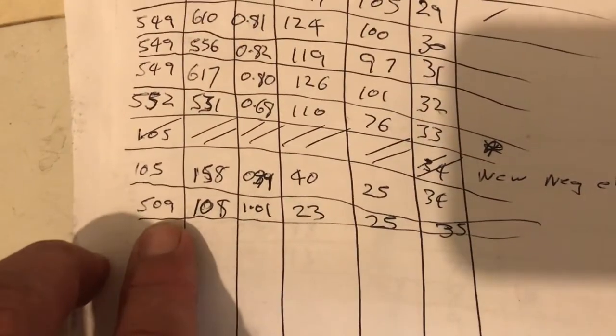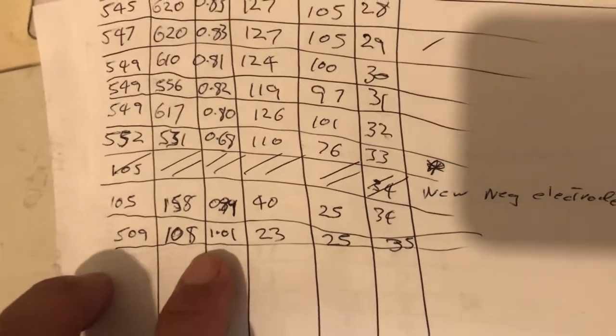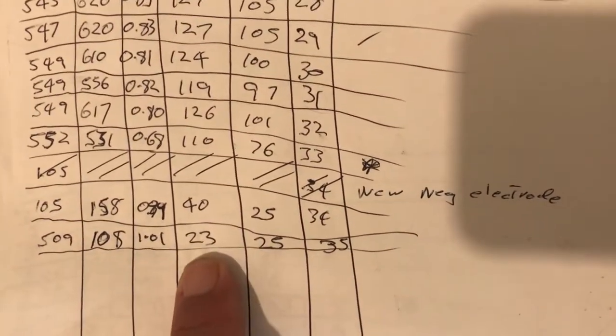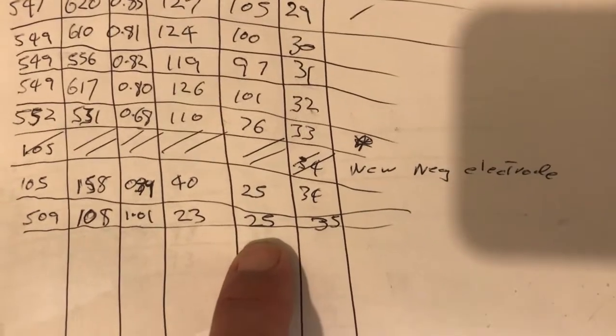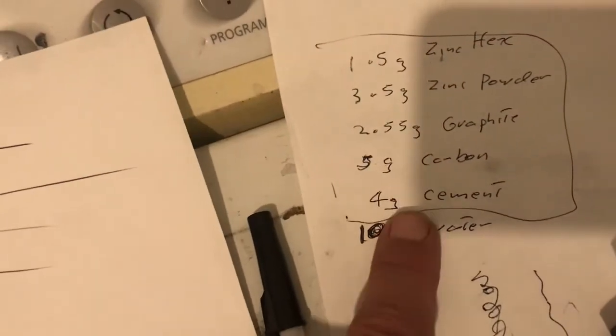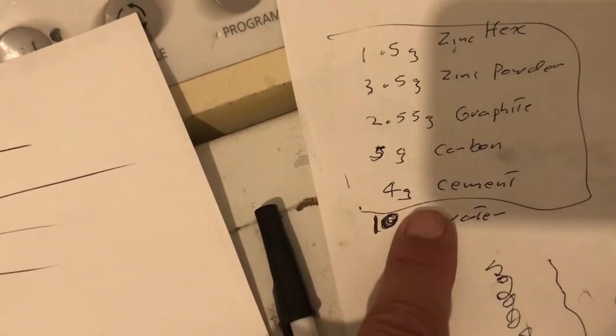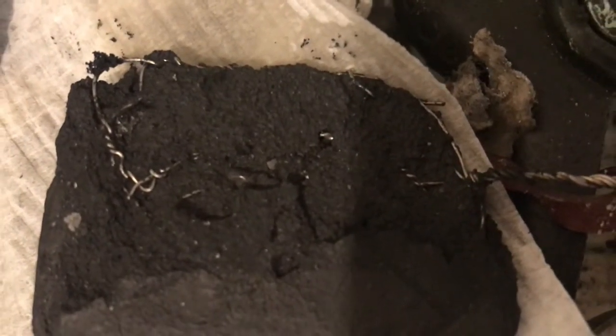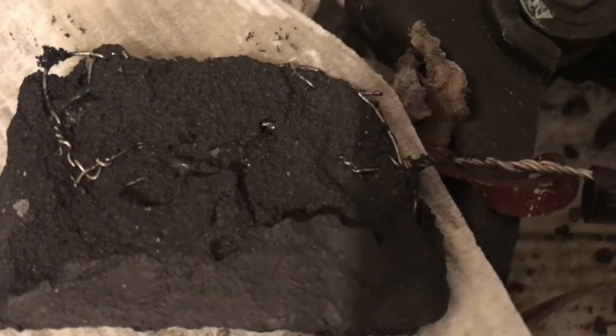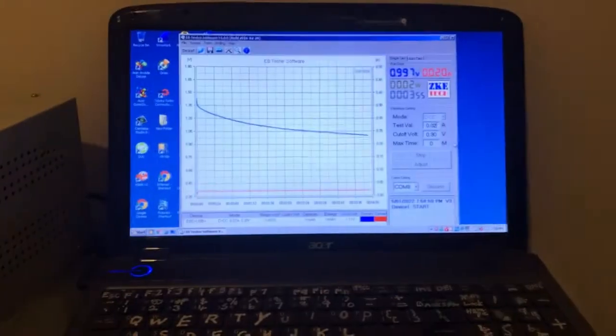For a 5 hour and 9 minute charge, only 1 hour and 8 minute run time, 23 milliamp hours and 25 milliwatt hours. I'm thinking this recipe needs to be adjusted because it was the first batch. That's what happened. It sort of dissolved away. And that's the remainder of the charge.